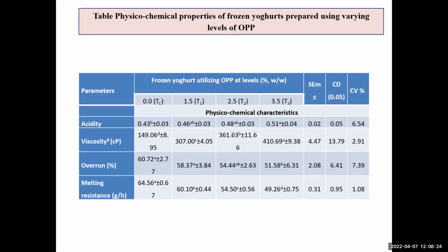Here in this table, you can see the physicochemical properties of frozen yogurts. In case of certain dairy products, namely ice cream as well as certain frozen dairy desserts, these physicochemical properties, mainly viscosity as well as the overrun and the melting resistance, are very important. Here you can see that the acidity increases from 0.46 to 0.5% lactic acid, while in case of the control, the acidity is lower. Definitely the orange peel is slightly acidic in nature, due to the contribution of citric acid. So that's why there is an increase in the acidity.